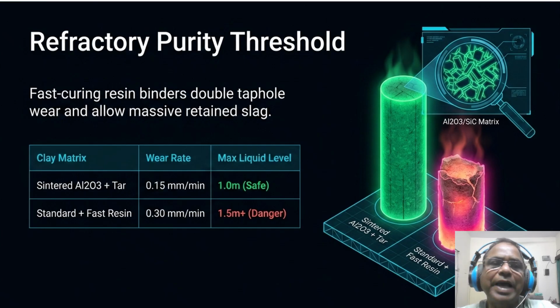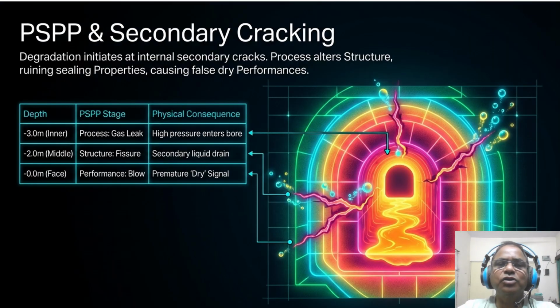the hearth pad. So excessive wear doesn't just happen at the face, it initiates deep within the structure through secondary cracking. So this slide is a cross section of the taphole bore. Notice the glowing concentric rings representing the PS stages: process, structure, performance. So look at the depth marker at 3.0 meter. We have high pressure gas leaks. At 2 meter, structural fissures lead to secondary liquid drains, and finally at the face you get a performance blow or a premature dry signal.